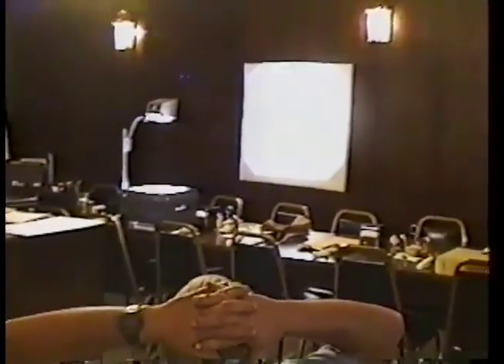So when we receive the liners, we should clean them? Very definitely. The best way to clean them is just hot soapy water and a brush. The hotter and soapier the better. Because what you might be seeing in your grind, in those liners that you can't find a crosshatch in, is grinding debris packed into the porosity of that chrome that's finally coming out in the operation. That's why grinding isn't really recommended for chrome, but a lot of people do it because it's the only way they can do it.